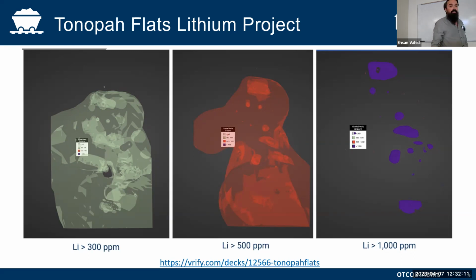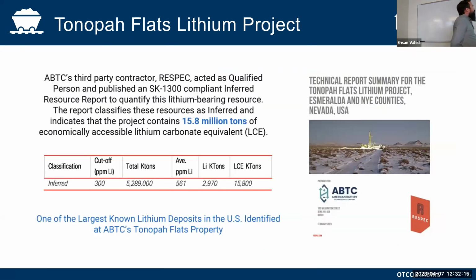Looking at all of this, we recently had a third party conduct our inferred resource report, which is SK 1300. This was done by Respec, a company located here in Reno. Going through all of the data collected through our drilling campaign and pit optimization, they classified the resource as inferred and indicated that it potentially contains almost 16 million tons of economically accessible lithium carbonate equivalent. That means we have a cutoff grade at 300 ppm, and in terms of lithium metal, that's 2.9 million tons of metal in this deposit. This is one of the largest known lithium deposits identified in the United States.